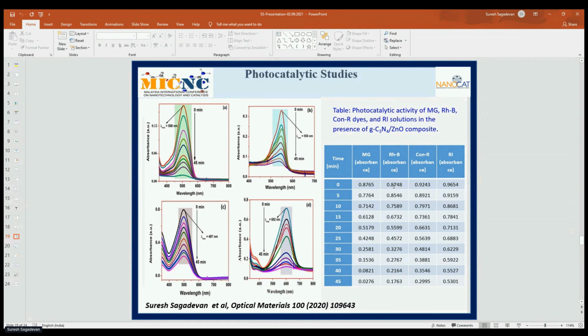From this table, you can clearly see that the composite has activity against all the dyes and solutions tested. It is getting reduced with increasing time period. You can clearly understand this from the table. The reason is the loss in the number of active catalytic sites. Further, among all the dyes tested, we observed the highest absorption for the red ink solution, followed by other dyes like Congo red, malachite green, and rhodamine B.